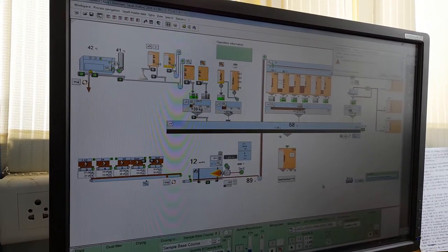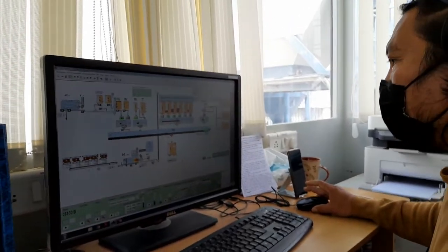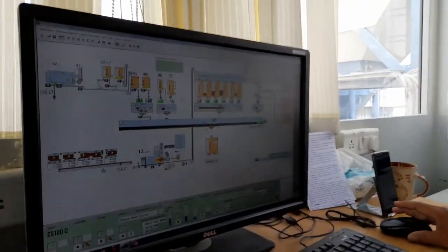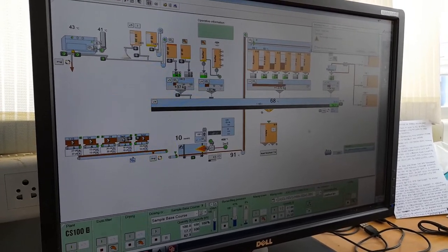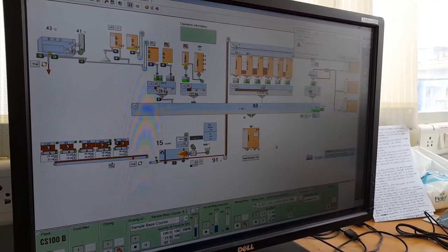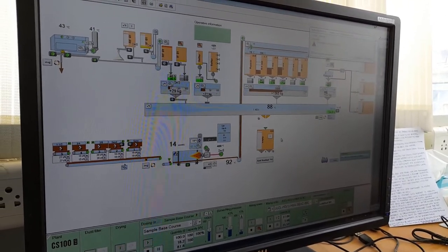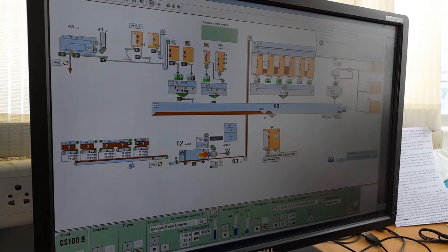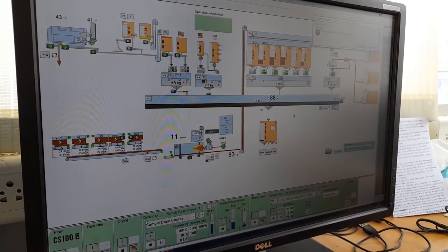But I have my own technique, because mostly for the first batch, we cannot be sure that all material from here is heated well. To make sure that the materials are mixed well here in the mixer unit, you must put some extra seconds before you open the gate manually. First batch, finish. The batch weight design for this recipe is 1.5, which means your finished product is here, 1.5. And the second batching is already inside the mixing unit.